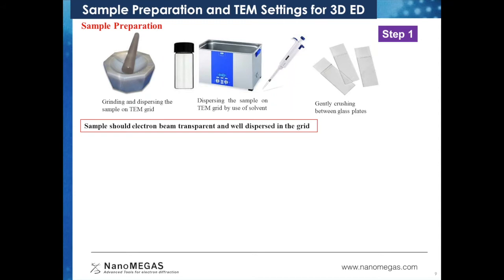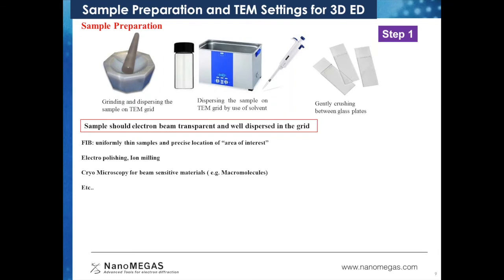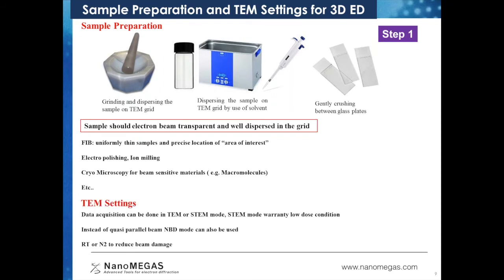But the most important thing everyone needs to keep in mind is that the sample should be beam transparent for an electron diffraction experiment. And for the TEM settings, the electron diffraction data can be acquired in TEM or STEM mode. STEM mode with low dose condition is recommended, especially if we are working with beam sensitive materials. Because in STEM conditions, one has a much lower electron dose than in TEM mode.